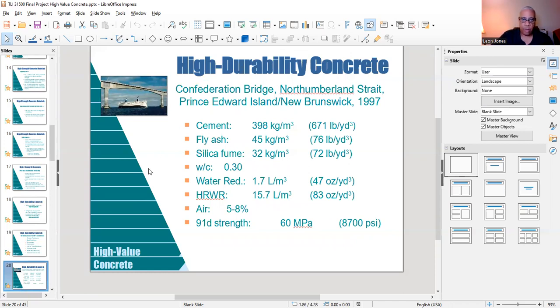All right, high durability concrete. Now this is actually a product, the Confederation Bridge in Northumberland Strait, which is between Prince Edward Island and New Brunswick. And here's the data. In that mix, the cement, 671 pounds per cubic yard, fly ash, 76 pounds per cubic yard, silica fume, 72 pounds per cubic yard, with a water cement ratio of 0.30. Then you also have water reducer, 47 ounces per cubic yard, and HRWR, which is 83 ounces per cubic yard. And your air, 5 to 8%. And generally your strength, 8,700 PSI, which is really strong.